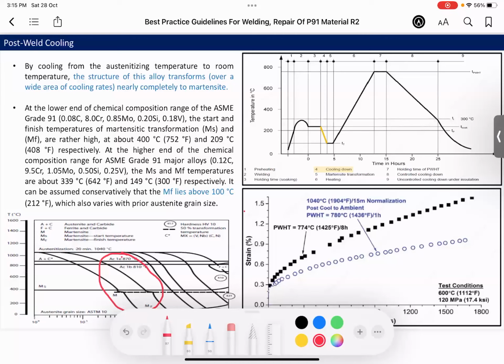But I should emphasize here that after cooling, it should be sent directly to PWHT. There should be no time between bringing the temperature down to ambient temperature and PWHT. The moment we reach room temperature or ambient temperature, we should go directly for PWHT, in part because this can create stress corrosion cracking if it is exposed to moisture or exposed to sulfur species. And we can see here on this graph the difference in creep resistance between two materials with post-cooling and without post-cooling. So the material with post-cooling shows that we have a better creep resistance.